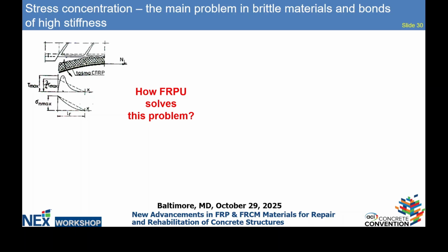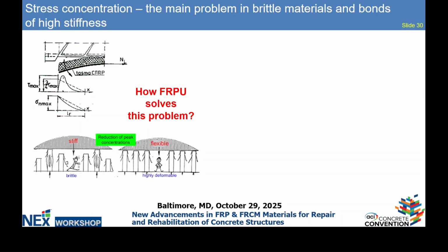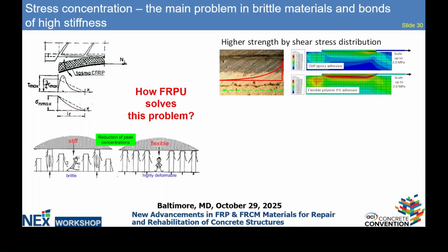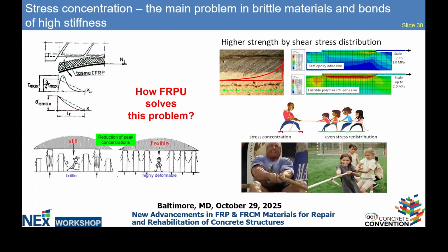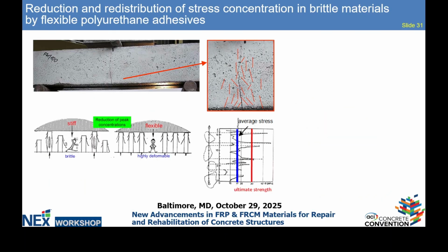So how to solve the problem of the stress concentration? It is quite easy because we should redistribute the stress more evenly when we use flexible adhesive. If we are considering shear stress, of course, we have stress concentration related mostly to stiff epoxy adhesives. This is here, but when we use flexible polyurethanes, we redistribute the stress more evenly. This is like the competition with a rope. On one side, you have a strong guy. On another side, you have children from kindergarten. Who will be the winner? 100 children should be enough.